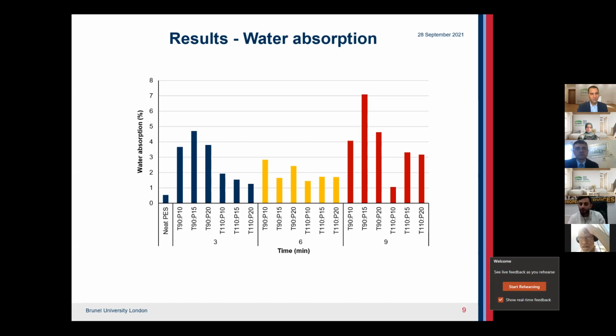So all the 9 minutes duration processing techniques showed an increase on the water absorption. However, if we take the 9 minutes on the 10 tons along with 110 degrees, it shows a very low water absorption and almost lower than the rest. So the microstructure of the composite developed should be analyzed very carefully in order to understand the phenomena behind this.